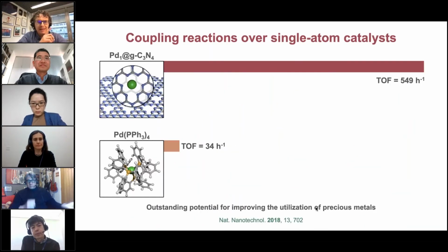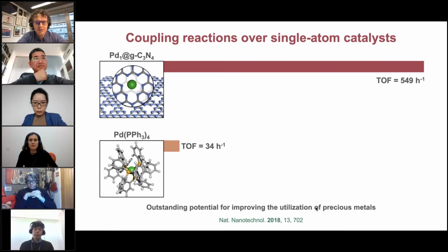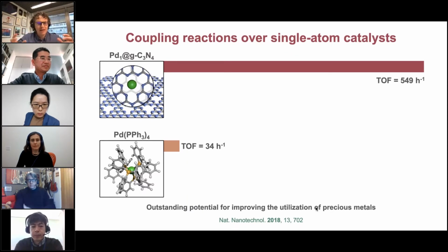Well-defined atomically dispersed metal-based catalysts bring exciting opportunities in traditional heterogeneous catalysis, but also beyond. A single-atom heterogeneous catalyst, a very low nuclearity catalyst like what you see here, palladium stabilized on 6-fold nitrogen cavities of carbon nitride, exhibits much higher turnover frequencies for Suzuki couplings compared to commercially applicable palladium triphenylphosphine. The potential replacement of homogeneous catalysts by well-defined heterogeneous analogs achieves a similar level of molecular precision, with a metal center surrounded by a stabilizing ligand, in this case the nitrogen sites in the solid scaffold, opening thrilling avenues for nanocatalysts in the field of fine chemicals and pharmaceuticals.